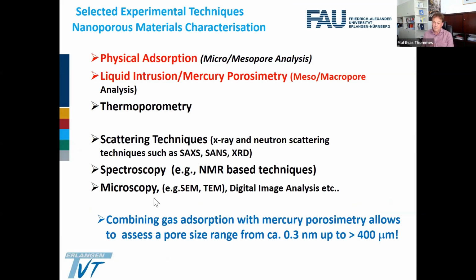But the interesting part is that these three methodologies, which I wrote up here a little bit separated from these, physical adsorption, intrusion, and thermoporometry, they all utilize the effect of confinement on the phase behavior to do essentially pore size analysis in particular. So if you have a wetting fluid which wets the surface, and we're thinking about the mesopore, then we're looking at the effect of confinement on the vapor-liquid phase transition or wetting film.